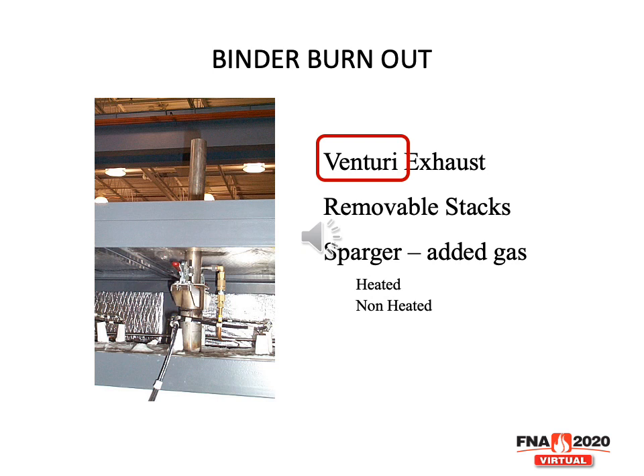We use a principle sometimes called Venturi, and Venturi exhaust, to help remove gas from the furnace and control the direction that gas goes in the furnace. Sometimes they have removable stacks. Sometimes we actually put sparger in, which add gas that can be heated or non-heated. This helps control the O2 levels in the furnace. And sometimes you need to pull a binder out, for example, in an area where you don't want to contaminate the furnace. You put one of these in.